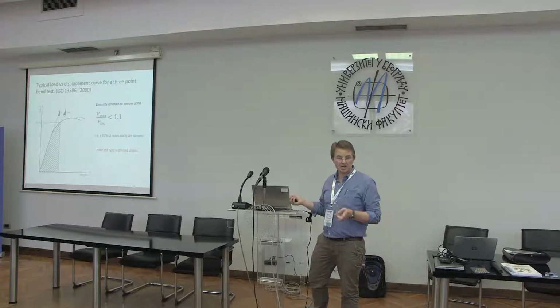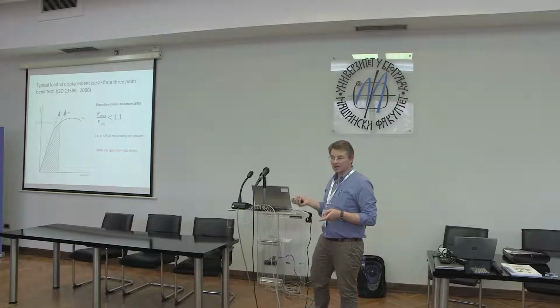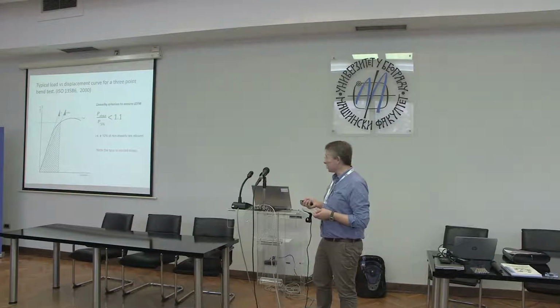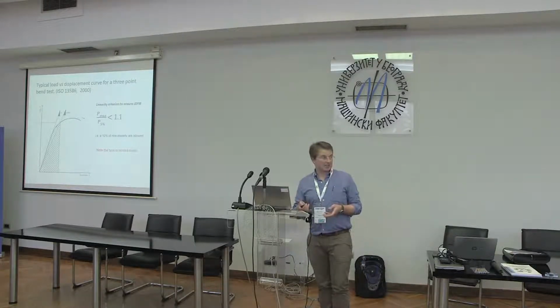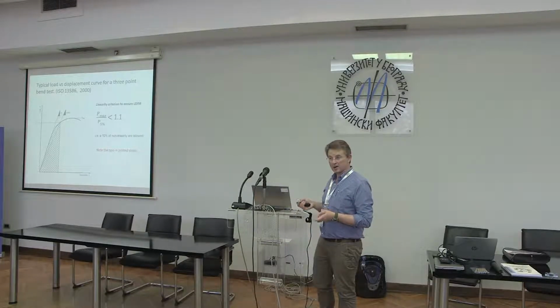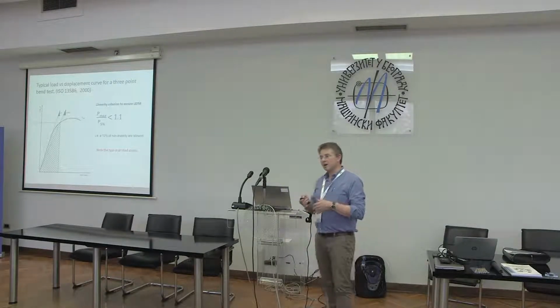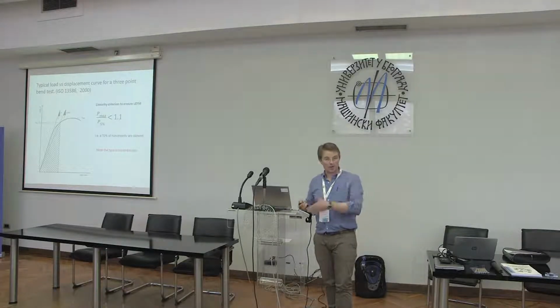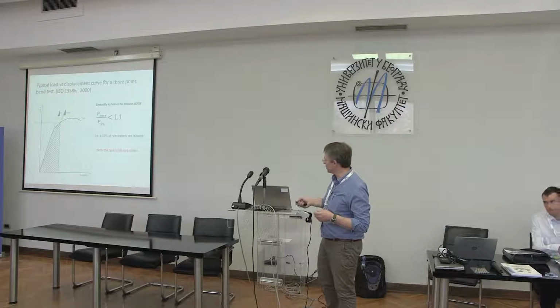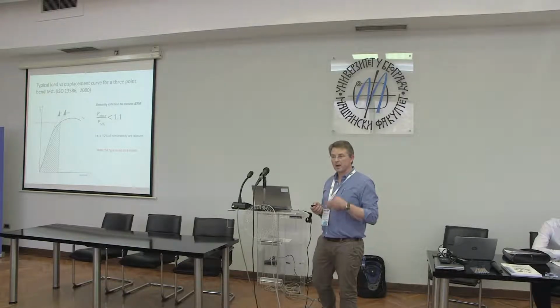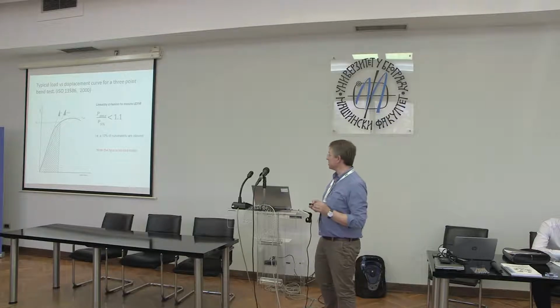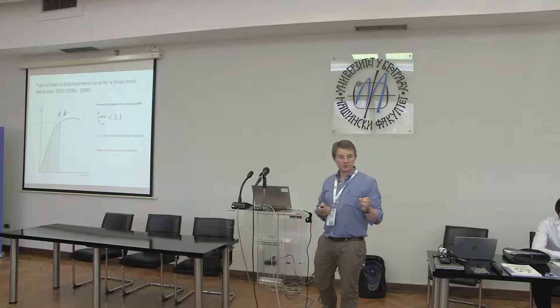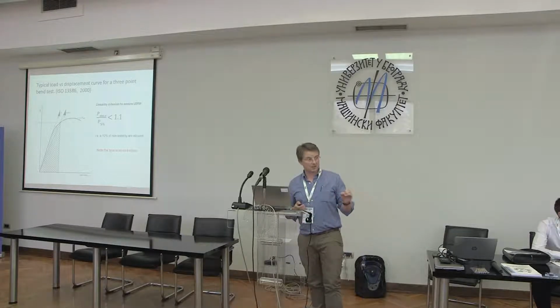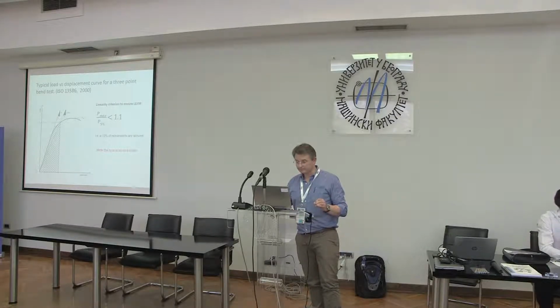So where does the non-linearity come from? It could be non-linear elasticity of the specimen. Okay, it could be general viscoelasticity, or it could be plasticity at the crack tip, or it could be, of course, initial crack tip growth prior to catastrophic fracture. So there are a number of sources of any initial non-linearity. But what we do is we pick out our maximum force and our 5% force here, and it's that 5% force, provided it occurs before the maximum load point, we use for the data analysis. So that's totally standard and taken from the metals approach.